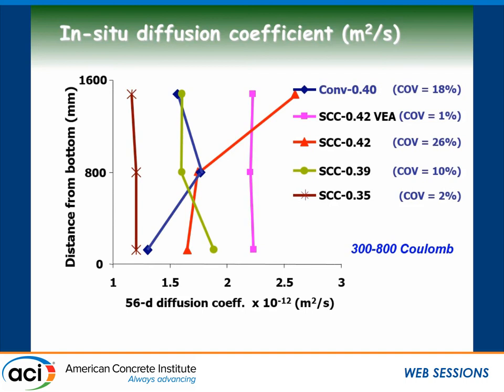So what Mr. Yazbek is saying is that when you didn't have any VMA, the 0.42, this is the in-situ diffusion coefficient, and when you added the VMA, you have a larger one. One thing, all of these concretes had very low coulombs. So when you add a VMA, VMA is an ionic product. It's a polysaccharide. It's going to have more ionic charge. The more ionic charge, you're going to have more diffusion. But still, those values, anything below 2.5, 10 to the minus 12, is very, very durable.